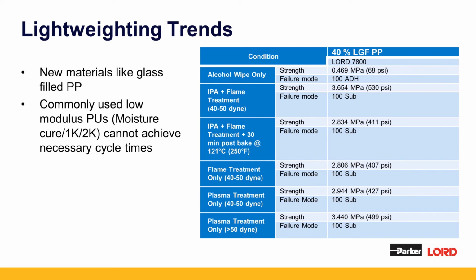It's only about 32 dynes, and you can see, as expected, adhesive failure, fairly low strength. But either with a flame treatment or a flame treatment where we did a simulated paint bake cycle of 30 minutes at 250 Fahrenheit or 121 Celsius, a flame treatment only or a plasma treatment only, you can see we achieved stock break in all cases.